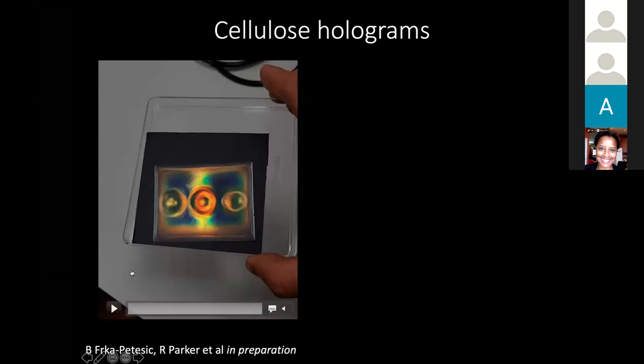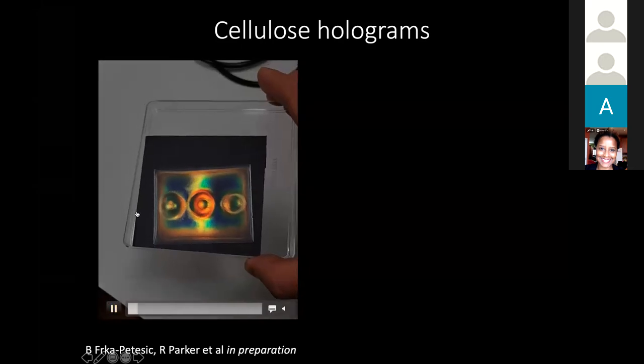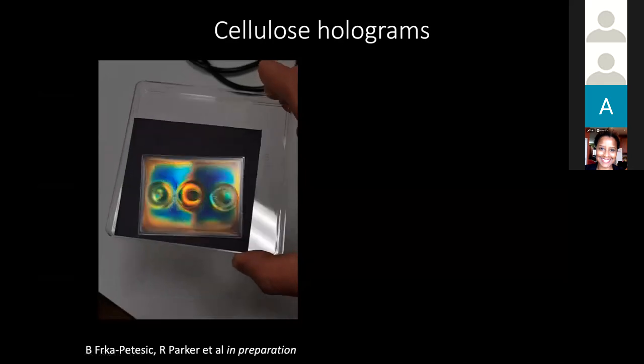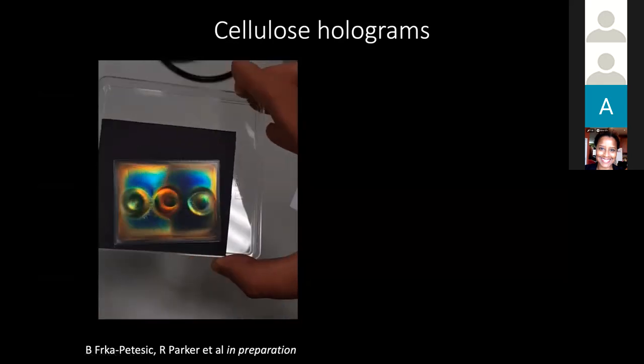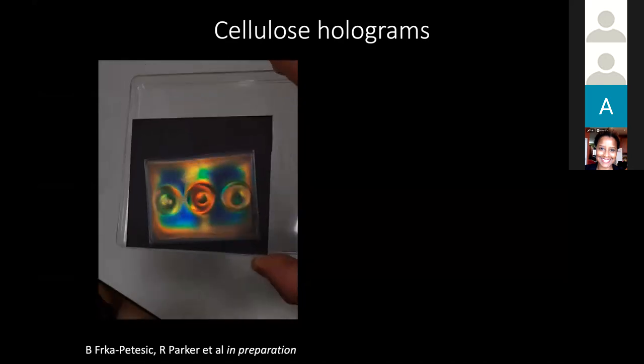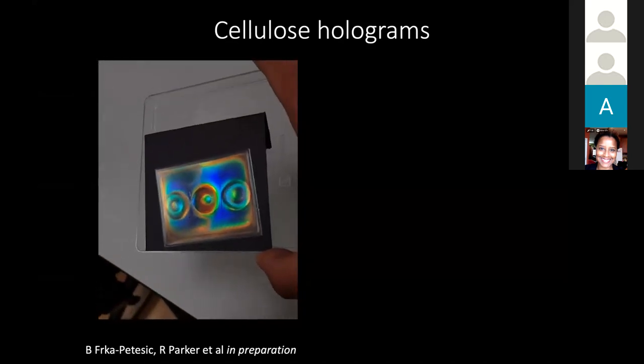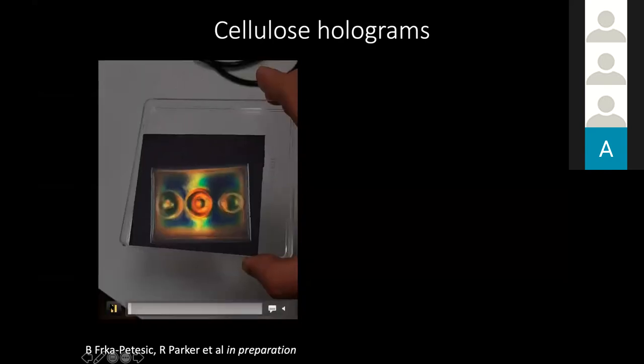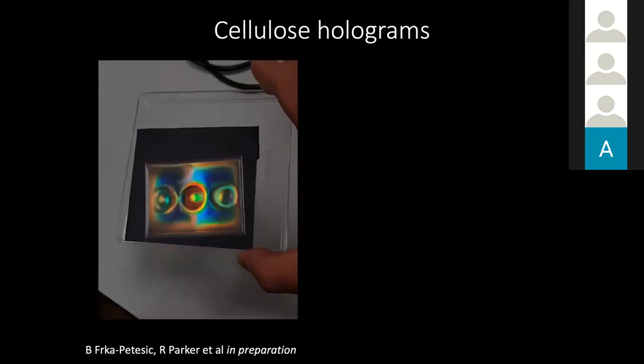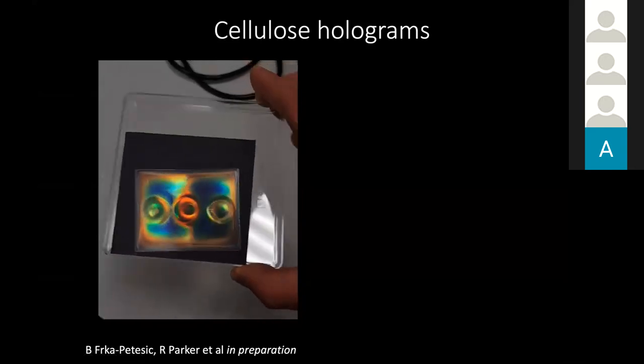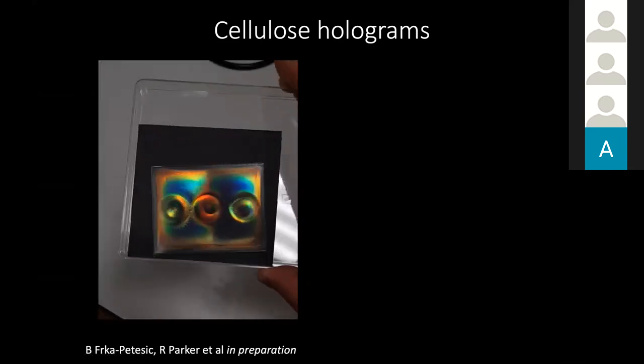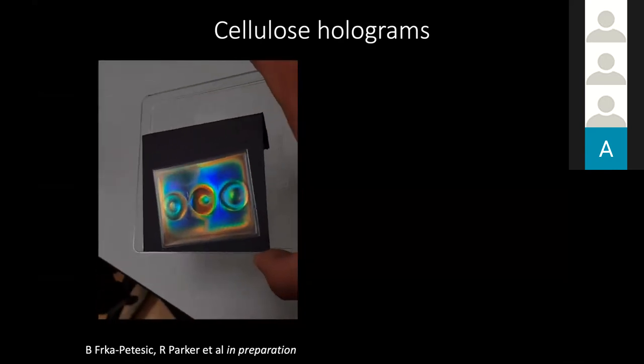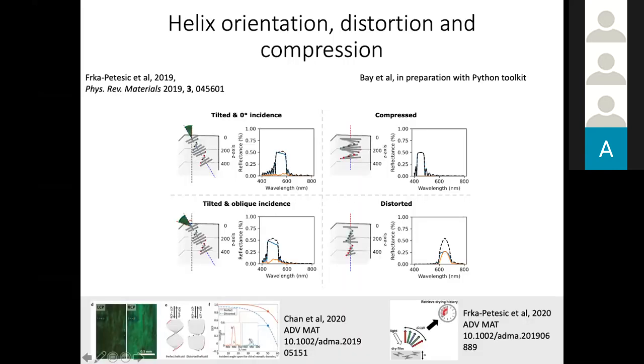And why this is cool, I'll show you in a moment, because this is, for example, a film. We call them cellulose holograms, because this is a film that is cellulose, and the color that you see here now, when you rotate, you kind of have the impression that the structure that you are looking at on this glass slide is three-dimensional. And this is essentially a hologram, but it's a hologram that is simply obtained using only cellulose. The only thing that we do is that we are able to really change the orientation and the twisting angle of this helicoidal structure within the film.